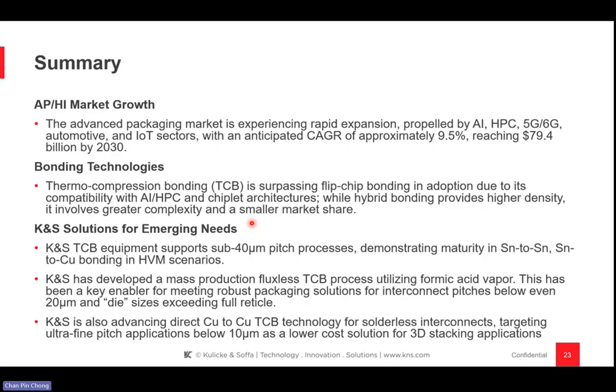goes to smaller pitch. K&S solutions: K&S TCB supports sub-40 micron pitch processes, demonstrating maturity for tin and copper bonding in high volume scenarios. And we are also in mass production on the fluxless process at different sites globally, utilizing the formic acid process. This is a big enabler for robust packaging solutions for larger die sizes exceeding the full reticle size, like I showed you in the roadmap for both CoWoS and EMIB. Today the pitches are less than 20 microns, and we believe we can scale down even to sub 10 microns with the TCB fluxless formic acid process.